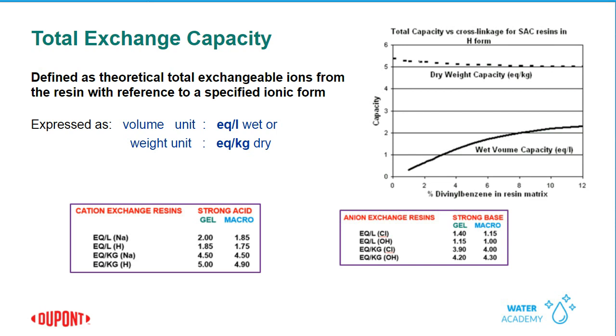And you'll note that they're different depending on what the form is. So for a gel, you may have 2.0 equivalents per liter in the sodium form, but only 1.85 equivalents per liter in the hydrogen form. And since this is a volume reference, this is because of what we talked about in the previous slide, that resins have a change in volume. So we're looking at in 1 liter, how many equivalents we would have. And so in the hydrogen form, the resin is going to be the most swollen, and in the sodium form, it's going to shrink. And so you can fit more beads in a liter in the sodium form than you can in the hydrogen form. And so that is why it appears larger, more equivalents per liter in the sodium than it appears for the hydrogen.